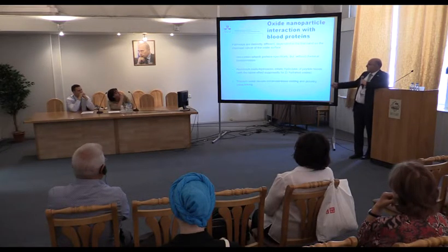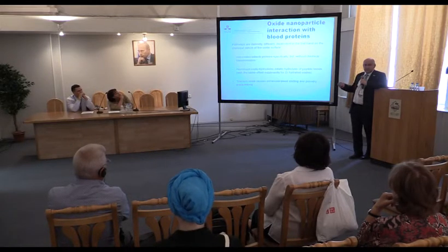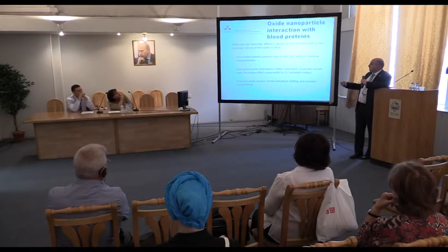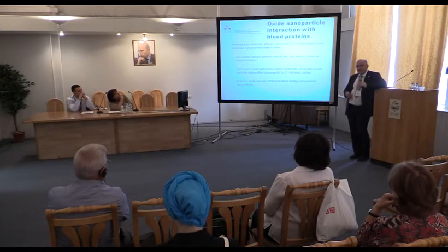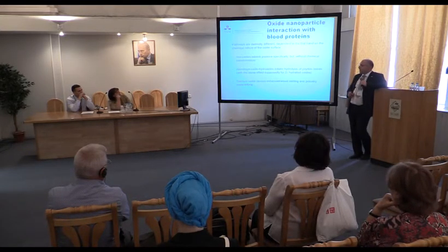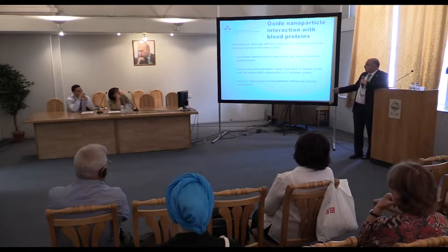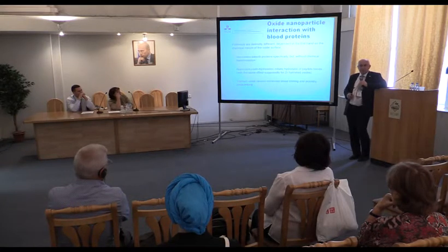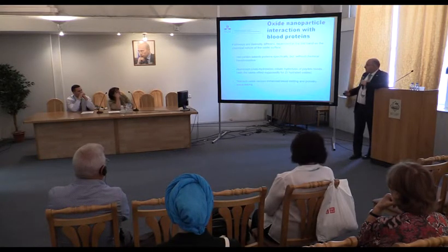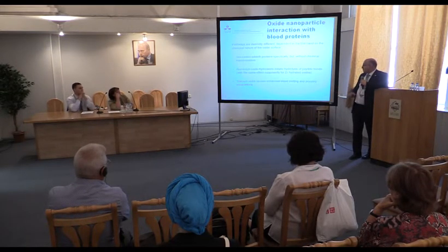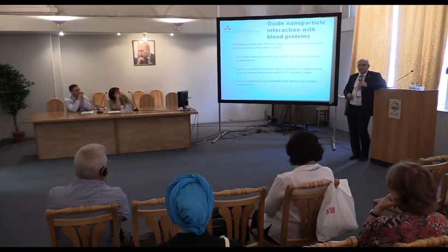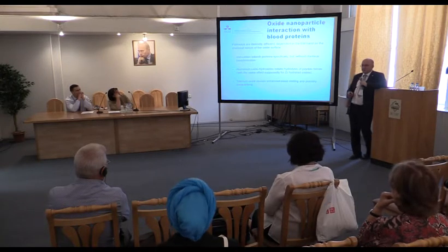In some cases, for example, iron oxides are adsorbing proteins, and supposedly specifically, I will show you an example, but without chemical transformation, so they do not cut the molecules, they do not build new molecules. Aluminium oxide hydroxides initiate hydrolysis of peptide bond. There are some very nice papers from our colleague at ITMO. And titanium oxide generally was thought to cause enhanced blood clotting, and there were some preliminary results of our colleagues from medicine faculty at Uppsala University from Rudbeck Laboratory.